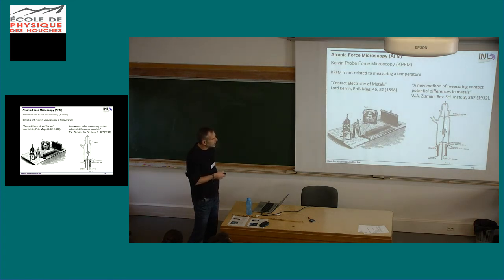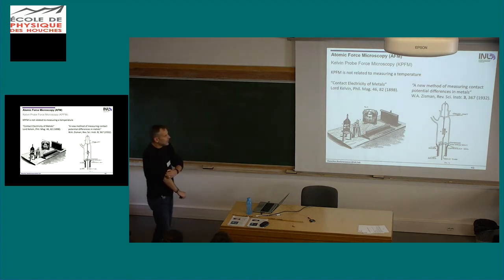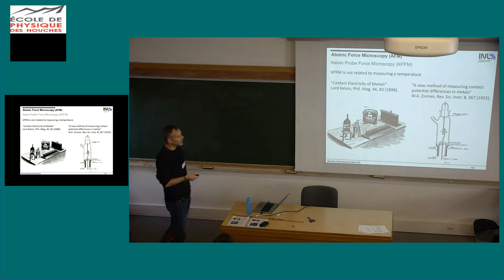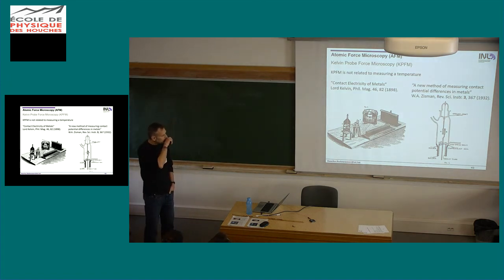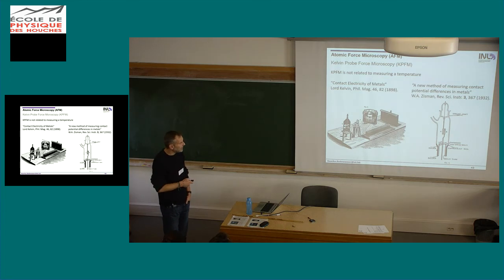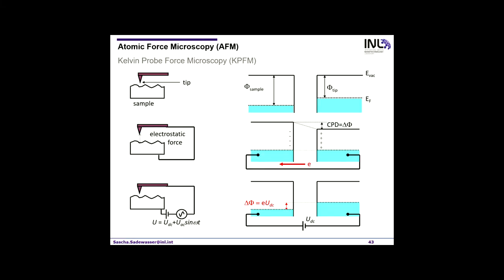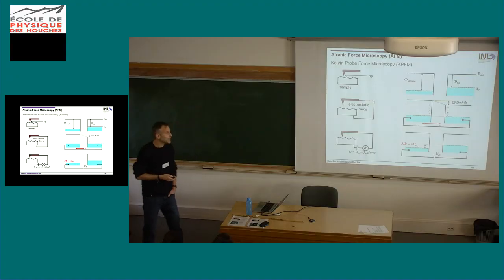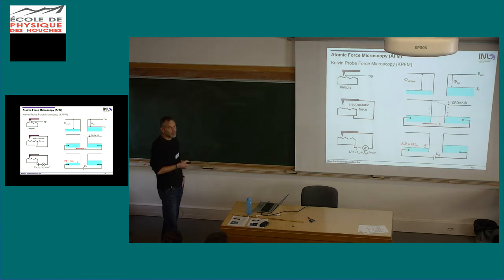So here it was this so-called vibrating capacitor method. So you still have your two plates with different metals. And then you vibrate one of the electrodes, and you use the displaced charges. So this is in the end a capacitor with a vacuum gap, and you use the displaced charges to measure the contact potential difference between these two materials. And of course in AFM we already vibrate the tip, so that's very nice. But it's not so easy to measure the charges because our tip is very small. So that's not the method we use in Kelvin probe directly, but our sensor here is very sensitive to forces.